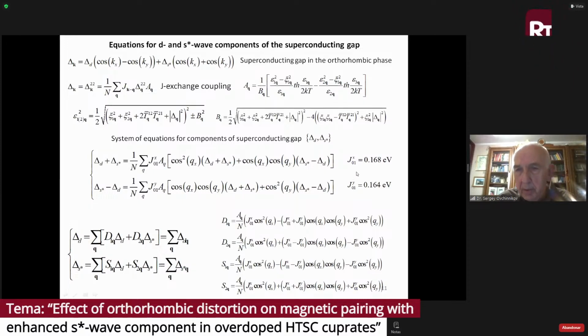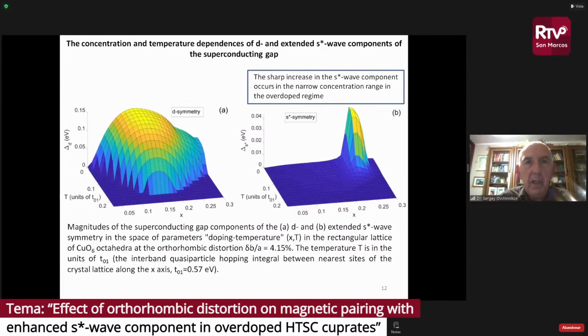Due to orthorhombic distortion, exchange interactions in the X direction and in the Y direction are a little bit different. They are shown here. And then we separate this system of equations for D gap and S gap. And finally, we get this linear system of equations for different gaps and for different doping and for different temperatures. And here is the solution of this equation.